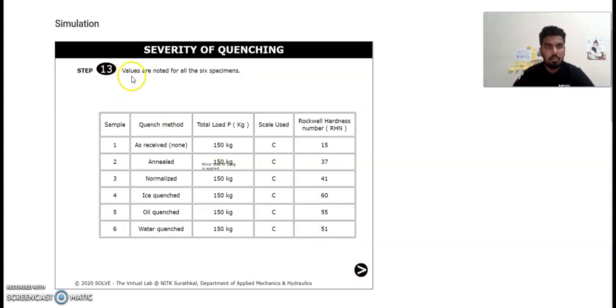Step 13. Values are noted for all the 6 specimens. Sample, quench method, total load P, scale used, Rockwell hardness number RHN. Sample 1, as received, 150 kg, scale C, Rockwell hardness number is 15. Sample 2, annealed, 150 kg, scale C, 37. Sample 3, normalized, 150 kg, scale C, Rockwell hardness number is 41.